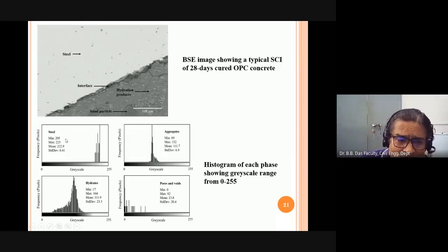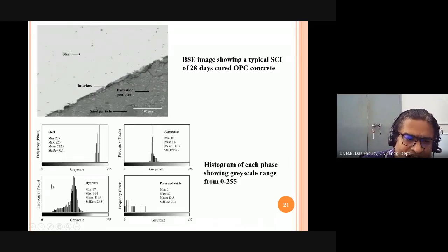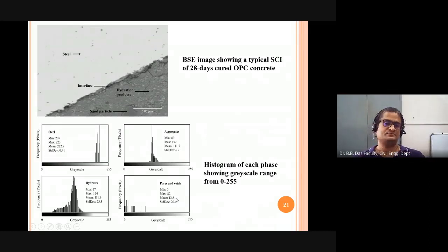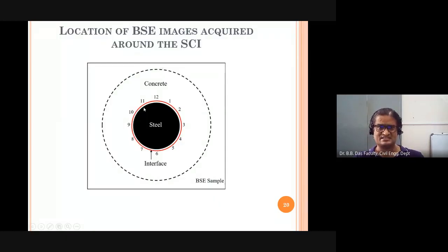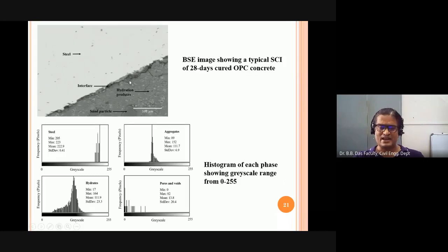So suppose I do the grayscale analysis for the steel. I am getting a mean of 222.9. If I go with the pure aggregates, the mean I'm getting is around 111.7. For the hydrates, the mean I'm getting is 111.9. And for the pores and voids, I'm getting a mean of 13.8. So that gives me an idea from this picture. This is my interface. So in this picture, can I separate the pores and voids from other materials?